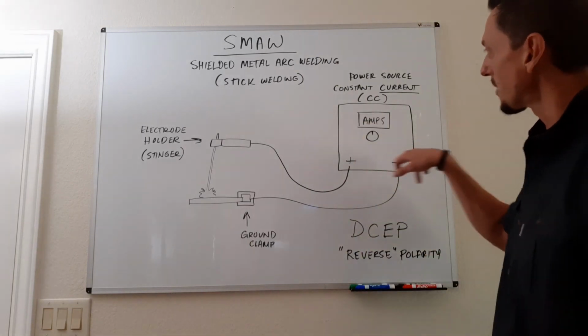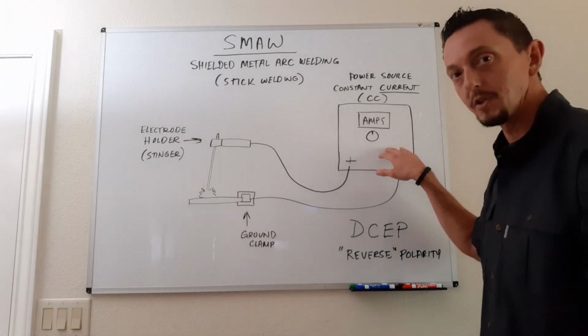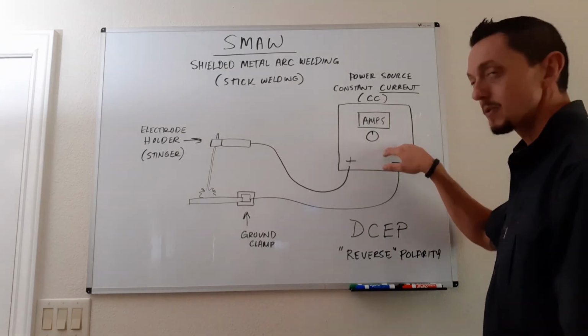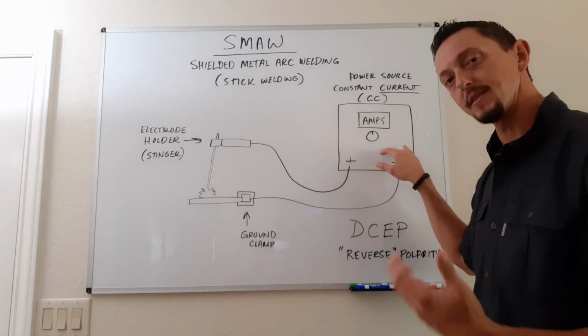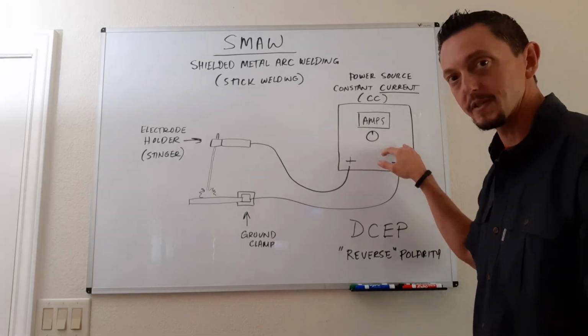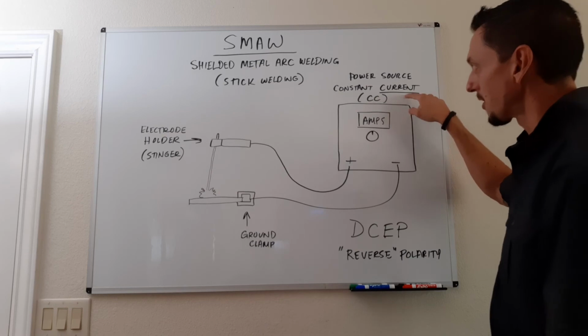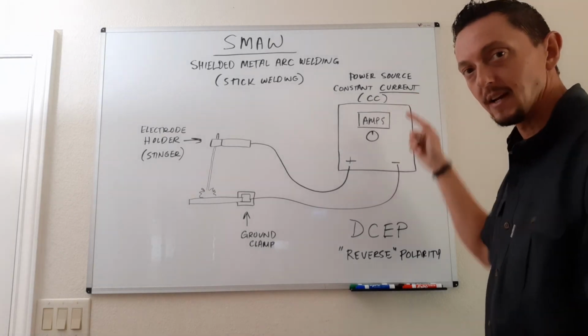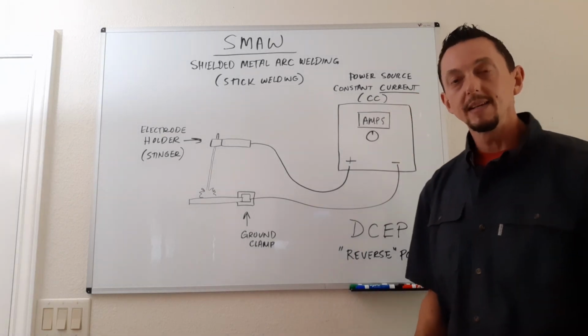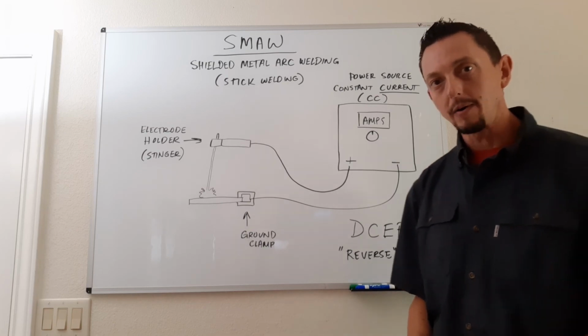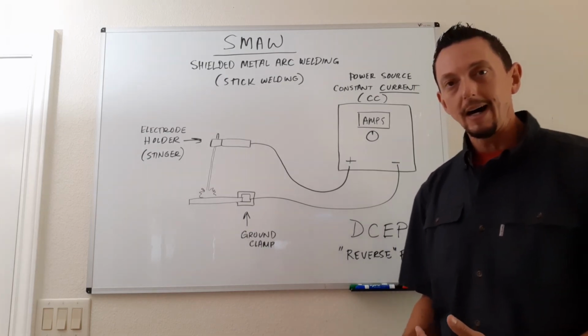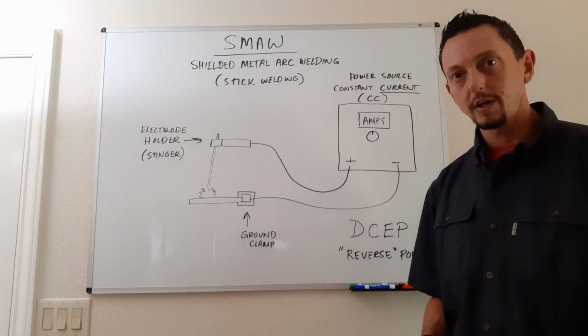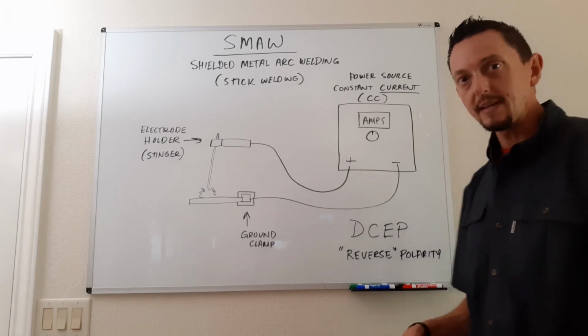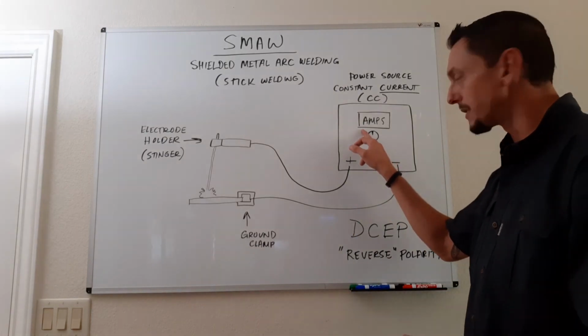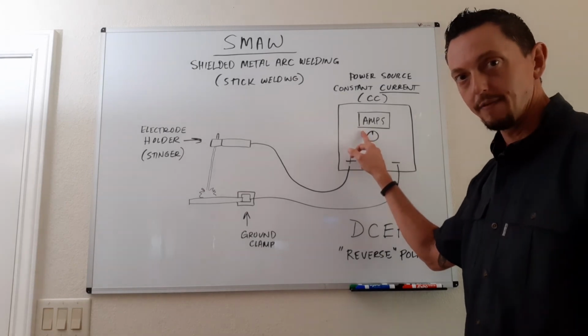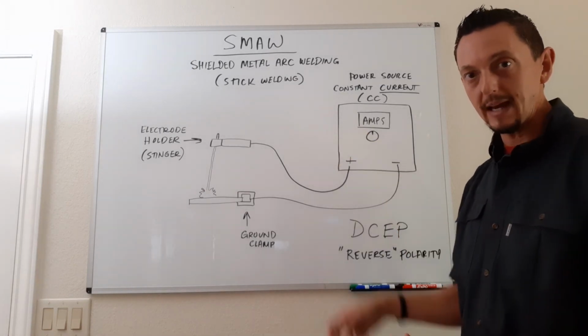So basically we're going to start with our power source. This would be your welding machine. The type of power source that it is is important because there's basically two different kinds of power sources. There's what's called a constant current power source and a constant voltage power source. In this case, we're using a constant current power source for SMAW. Another word for current is amperage. And we basically only have one parameter that we adjust on the machine for SMAW, and that would be amperage.